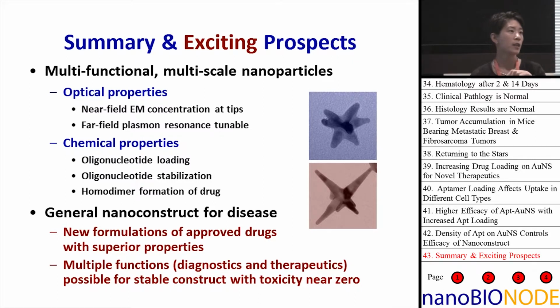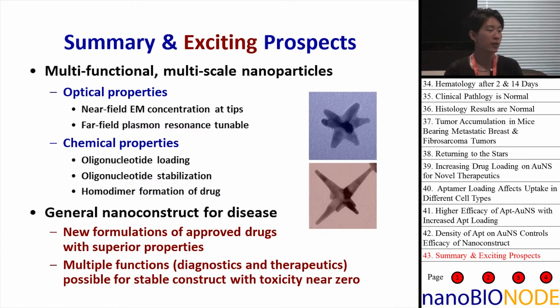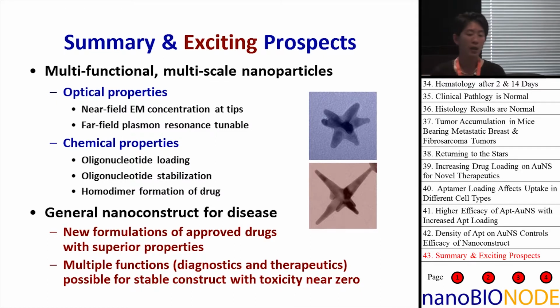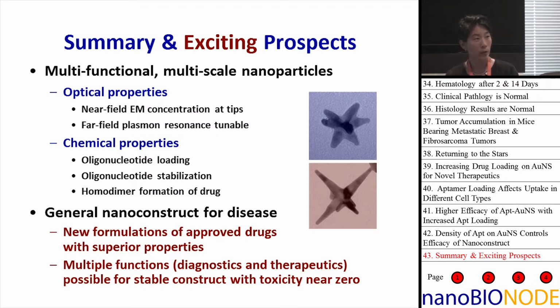But then we're doing the cell studies. They're in media, and media is complicated because they have all the growth factors for the cells, and it's got salts and all these other proteins. And so there's this thinking right now in the community, which people are trying to get around, that besides all of this beautiful engineering you've done on this particle, it's surrounded by something called a protein corona. So all of this non-specific adsorption of proteins that bind, and then you've done all this engineering, and then boom, it doesn't work at all. And so there are some challenges there that people are having in vivo.